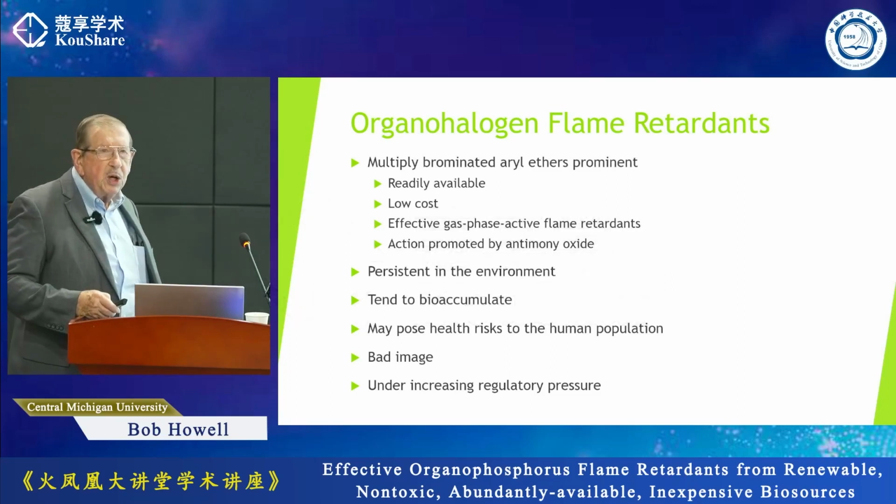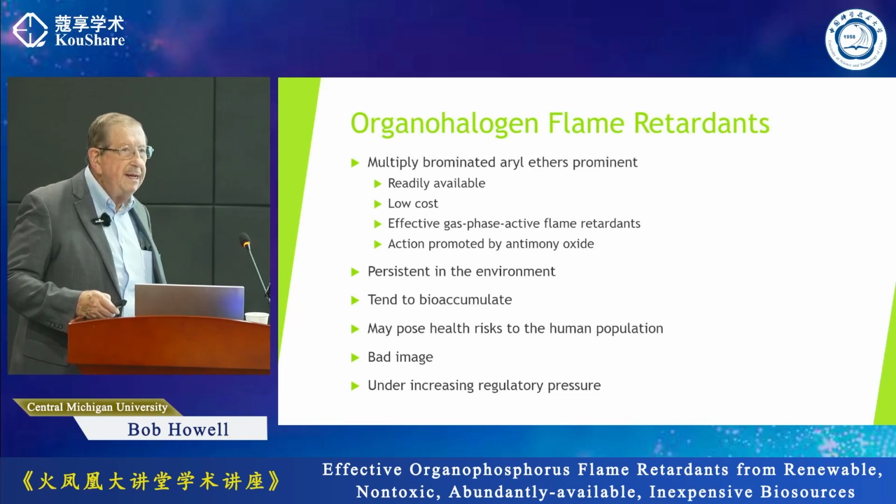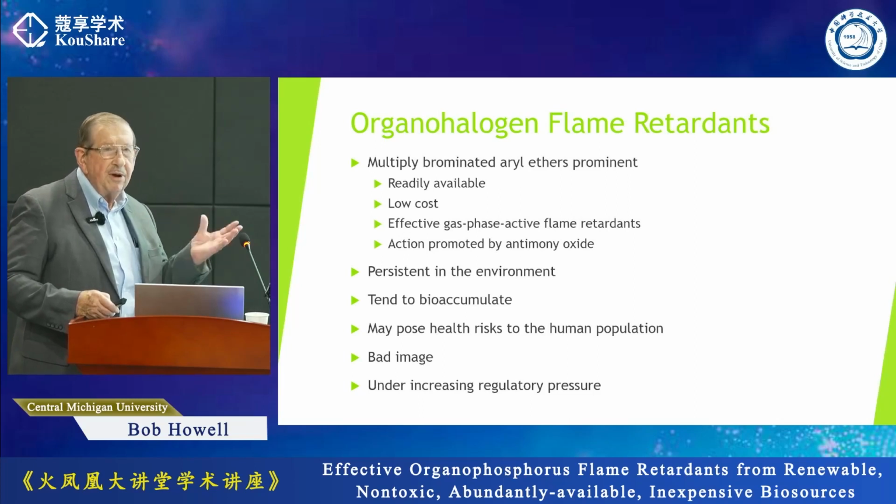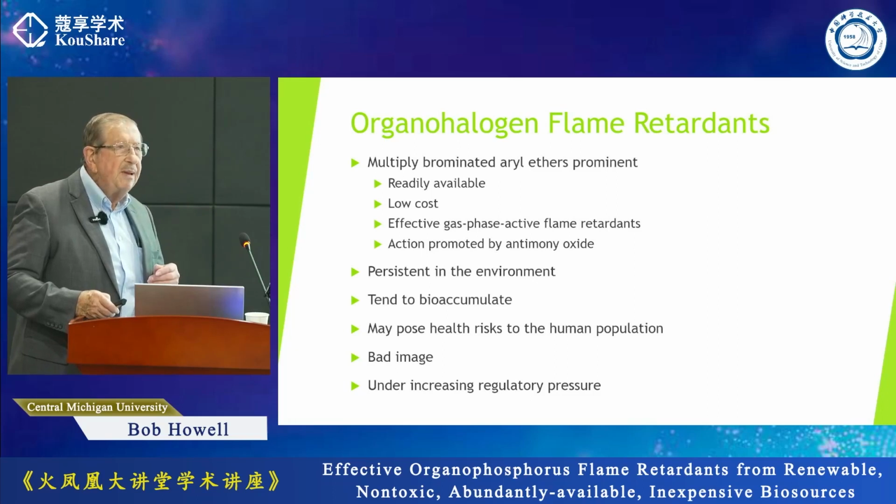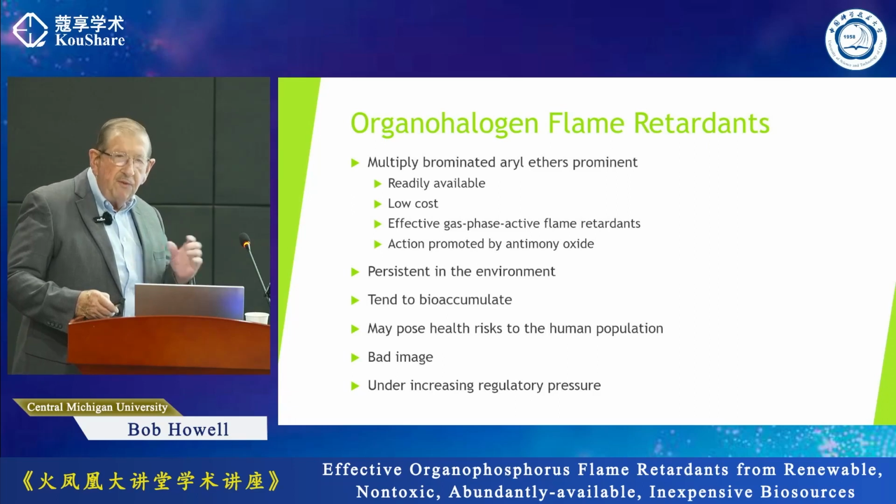The antimony oxide is toxic, particularly as a powder, and so there are many replacements being tried for this material. A problem is that many metal salts will form trihalides or form halides in the matrix, but they're not sufficiently volatile to be effective.